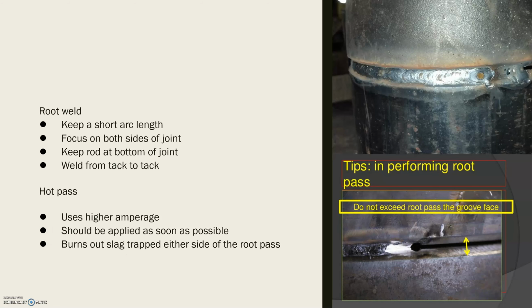Starting with the root, keep your rod jammed in where the land area is. Keep track of both sides of the joint and try to weld from tack to tack. Or later on, with a little practice, you can feather tacks out and burn right through them. The root pass is more brittle and prone to cracking. It absorbs carbon from the base metal. It cools much faster because it's a smaller weld.